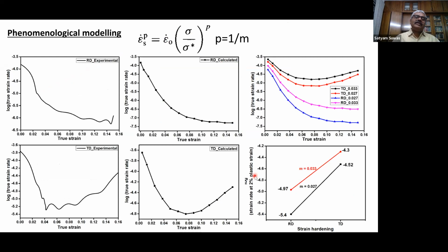And so these fatigue tests were also modeled, and basically the strain hardening, all kinds of modeling was done for strain rate versus strain under these cases. And we could see a very similar situation as in experimental cases. And of course, we could also see the strain rate sensitivity values as per our anticipation, as per whatever we experimentally calculated in that line.